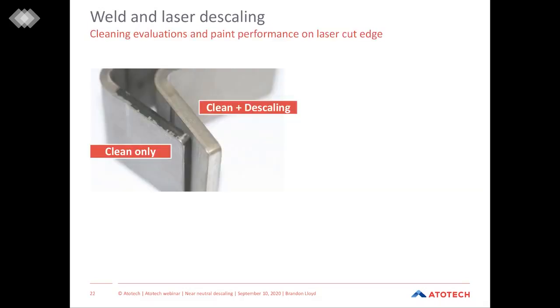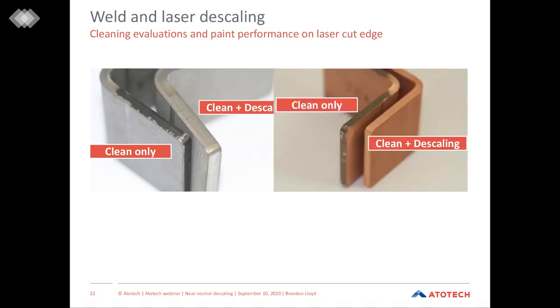Again, some more examples similar to what we saw earlier. So the part on the left will exhibit a clean only application where we see that the oxide scale is still on the laser cut edge. The part on the right is showing the cleaning and descaling where we have complete removal of the oxide scale. If we show these parts after the copper immersion evaluation, we can see that again the coverage on the oxides is minimal or none at all. And with the implementation of Uniprep AC, we get extremely good coverage on the laser cut edge because of the complete removal of the oxide scale.